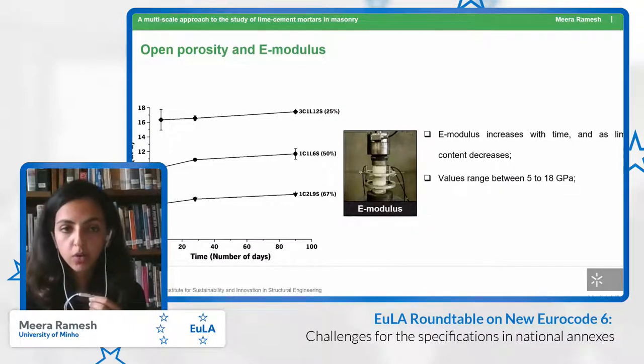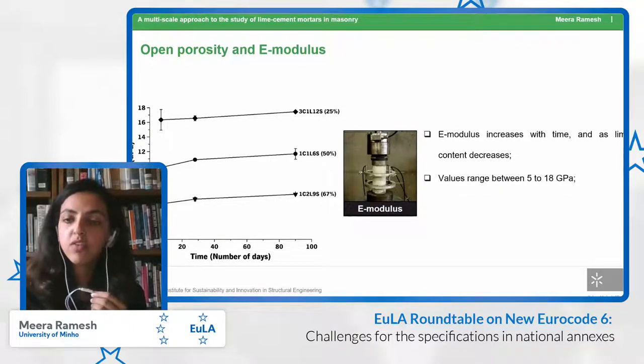Similarly, in the case of Young's modulus, as you increase the quantity of lime in the binder, we found that the Young's modulus reduced. So basically, a mix with more cement in it would be more stiff or would have a higher Young's modulus. And with time, the Young's modulus increased for all our mixes. The values that we found ranged between 5 to 18 gigapascal.